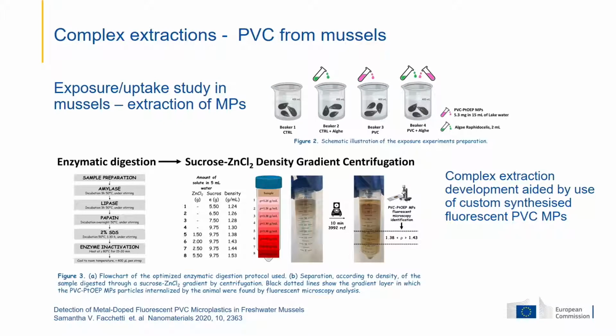I will just add here very quickly the situation of doing such analysis also with more complex samples such as that extracted from mussels. In this particular case, we had to look at an enzymatic process, as this was much less likely to damage the materials.